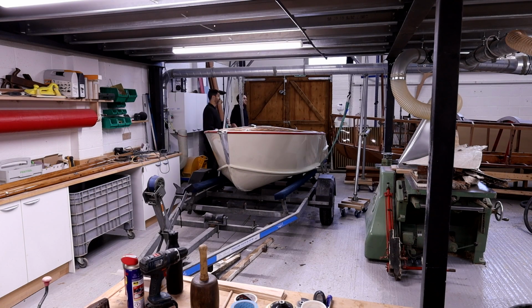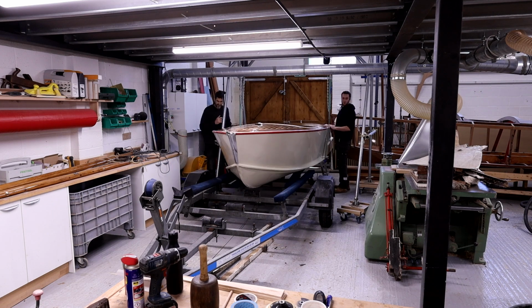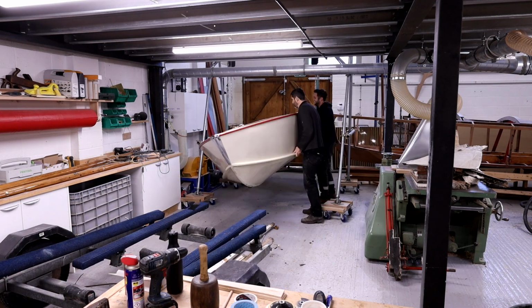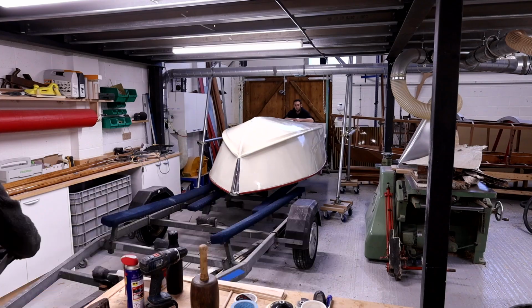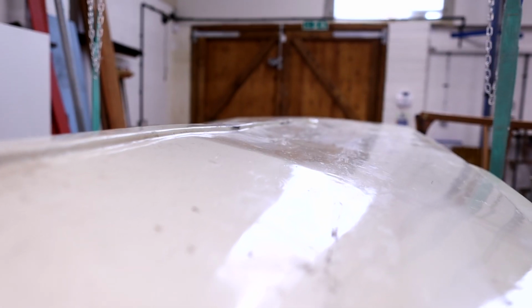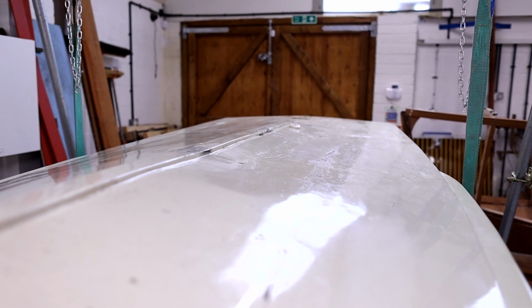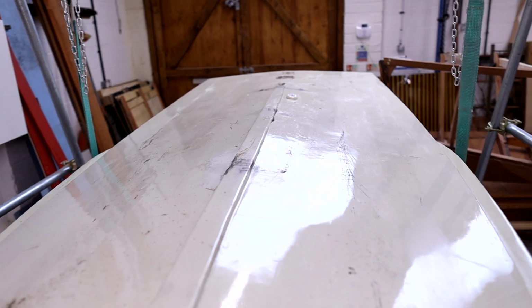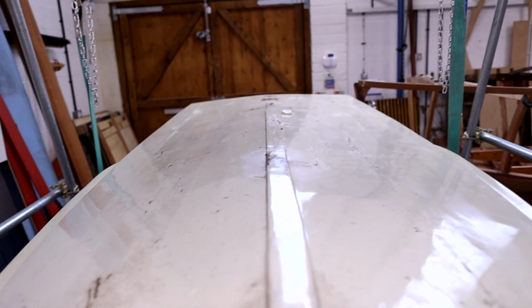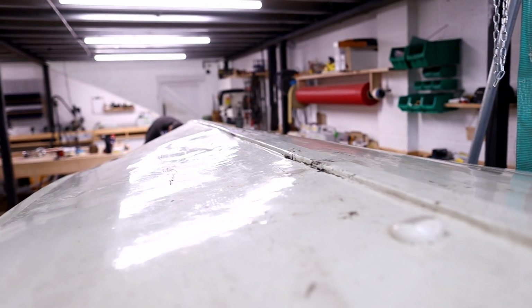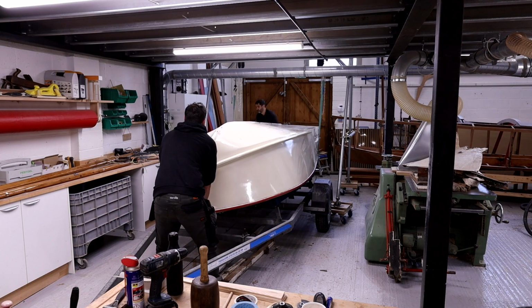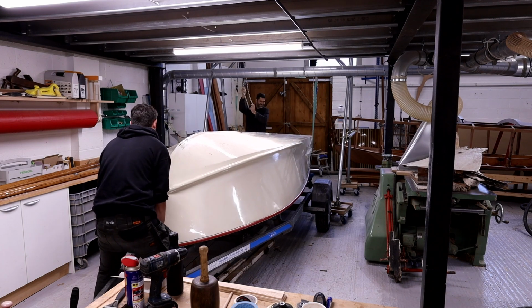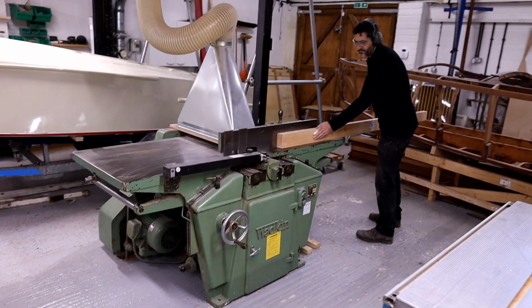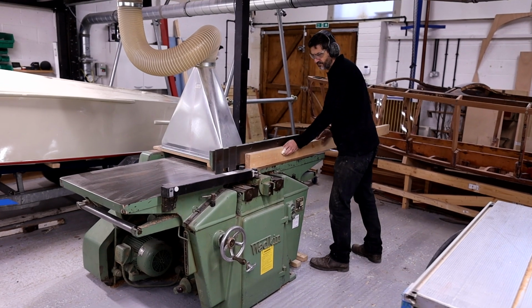So the first thing that we had to do was to get the boat turned over. We wanted to take a proper look at the bottom and see what was going on with the shape here, and as you can see the boat was pretty distorted. Once we got it upside down we could have a really good look at exactly what was going on there. And what we found was that one side of the hull seemed to be pretty much in the right sort of shape and the other side was quite badly distorted, where the boat had sunk down on the bunks on the trailer that it was sat on. The keel was also quite a bit out of shape, so the first thing to do is to get that straightened out.